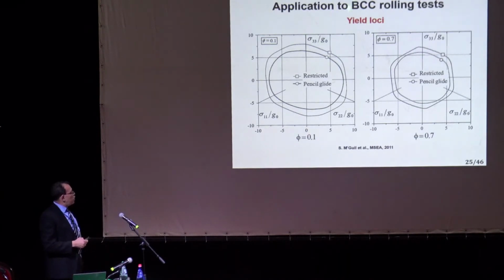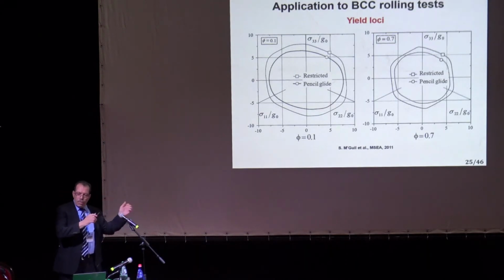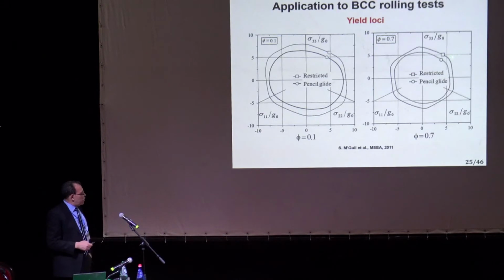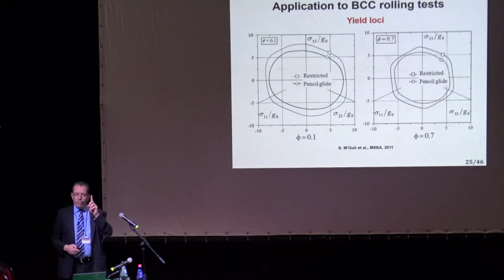This is one of them. This is for BCC materials, and we are looking into the yield locus or the yield function somehow. So this is the yield locus for phi equal 0.1 and phi equal 0.7. So these are 2 extremes somehow, closer to the lower bound and closer to the upper bound. And you can see there are certainly differences, big differences. Now, in FCC, we have the 111 planes and the slip directions are the 110, okay? And we have 12. In BCC, the major one is the planes 110 and the direction 111.